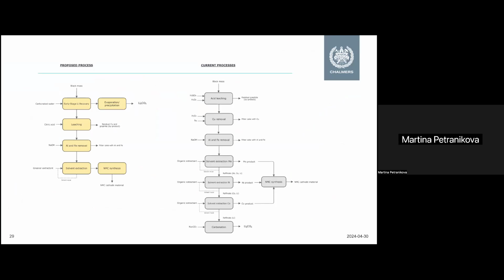And when it comes to the group which is working on the chemical recycling of the batteries, we have developed two routes. The gray one is the very traditional one, where we use leaching, then removal of the impurities, and then we go for the separation of the transition metals. But we also wanted to focus on something shorter and maybe more feasible and easier for the recycling companies. So the idea was to get the lithium first before all the other elements, then remove the impurities, then keep the transition metals together, and then go for the synthesis of NMC material from this mixture. So we can skip all the solvent extraction or all the separation of the transition metals. And with this one, we cooperate with the University of Uppsala, and they are helping us to make this NMC material.